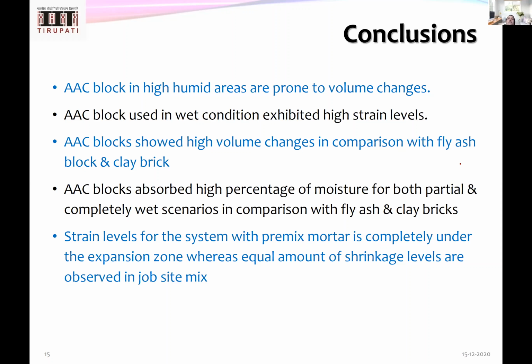When we start using job site mixers, what happens here is, I have two materials which have comparably two different behavior properties in moisture absorption. If I have two different materials and two different properties, relative movement is not freely allowed in the system, obviously cracks will happen. So here the entire presentation has discussed the possible AAC block cracking in the system and how this can happen. And AAC block as an infill wall only we have treated here. We haven't discussed anything about a load bearing AAC block.